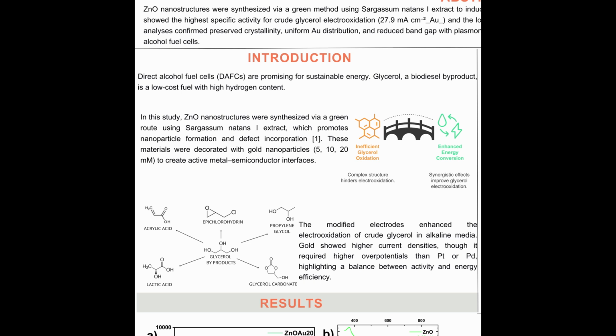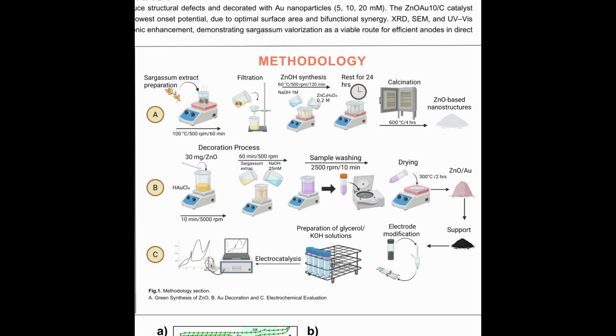Defect engineering in metal oxides is a proven approach to enhance electrocatalytic performance by increasing surface activity, electrical conductivity, and charge transfer kinetics. Zinc oxide is especially appealing because of its abundance, stability, semiconducting properties, and oxophilic nature, which promotes strong interactions with hydroxyl species. In this work, we employed a green synthesis route using Sargassum natans 1 extract to introduce structural defects into zinc oxide, followed by decoration with gold nanoparticles at different concentrations, aiming to create metal semiconductor interfaces that synergistically enhance glycerol oxidation in alkaline medium. The methodology was divided into three stages.